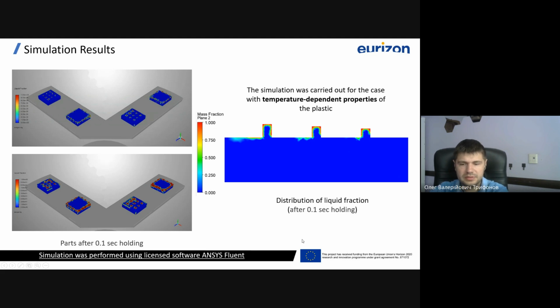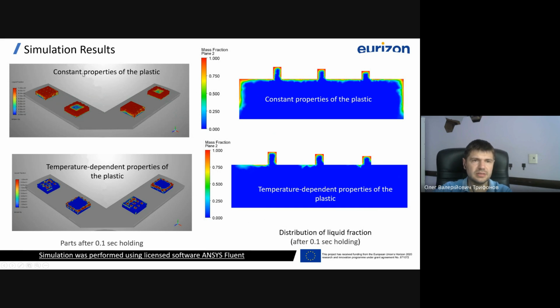And for some comparison, we can see that the influence of temperature-dependent properties is very important. For constant properties, during the same time, we have almost all surfaces melted. For the case with temperature-dependent properties, we melt only the small features of the part, like bars on the top surfaces and on the edges. The same if you look at the depth of the melted layer, we see that for constant properties it's much bigger.